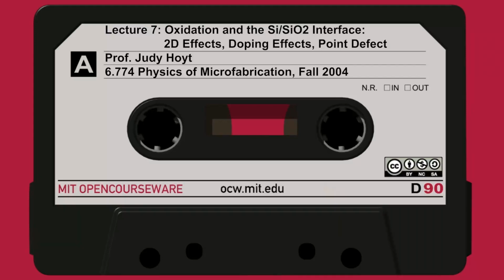So there are two different simulations shown here. Up on the upper right is without any stress, and you see the thickness of the oxide as you go around the corner is reasonably uniform. It doesn't change too much. With stress effects, look at the corner. The oxide thickness is quite a bit thinner here. It's thinned out in the corner region compared to on the flat surface or on the vertical surface. And this is a problem, because if that oxide gets too thin, you're going to tend to have breakdown effects, or it's going to affect the electrical properties of this device.